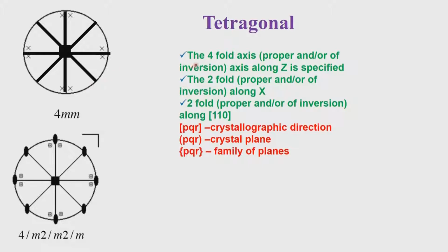So, the tetragonal system is characterized in terms of the first number associated with the z direction. We always have this along the z direction. The two-fold is then, since we have 4 2 2 as a possible combination of three axes. See, in tetragonal we can have only one four-fold axis alone, and that itself satisfies the condition required for a tetragonal symmetry. That means A not equal to, A equals B not equal to C, alpha, beta, gamma 90 degrees. So, that is a single axis operation.